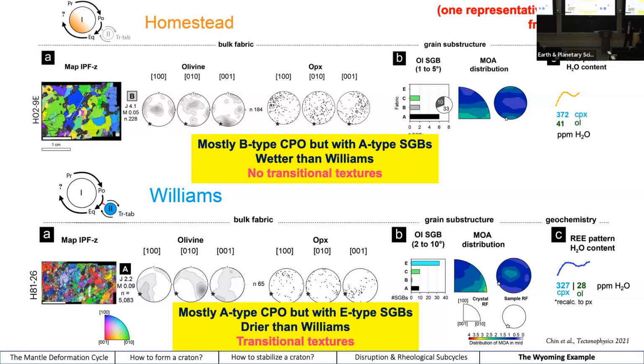We found no transitional textures. And we also measured water content through SIMS in all of these olivine and pyroxene grains as well. So we did conclude that the Homestead xenoliths did reflect wetter conditions, but the CPO subgrain stuff didn't match up. At the Williams locality, which is slightly more to the edge, we found similar discrepancy, lower water contents, higher temperatures also, and more of these transitional textures.